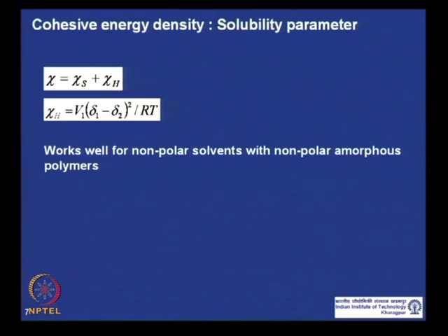So, from this expression also you can predict that the polymer-solvent interaction parameter would be lower than 0.5, which means the polymer will dissolve in the solvent you are using. Now, as I said before, this works well for a nonpolar solvent and nonpolar amorphous polymer.